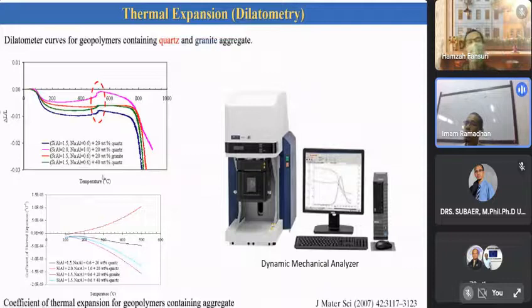Here, as a function of temperature, mostly you can only access up to around 800 degrees, because after that the material will shrink quite badly, so the gauge access of the dilatometry is lost. You cannot access the data anymore at more than 900 degrees Celsius. But what you can see here is that the coefficient is negative. It means that the geopolymer actually shrinks when you heat it up, say from 100 degrees. At low temperature, for example from room temperature to 100, the material will expand a little bit, and then it will shrink.